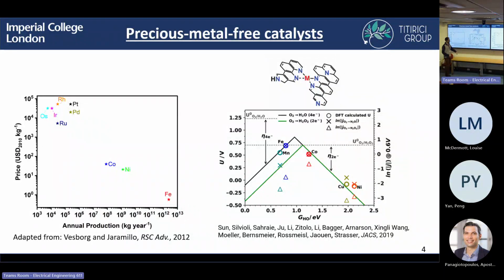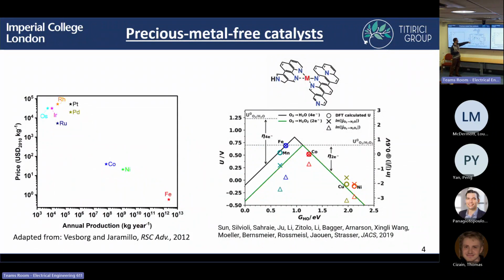And just to clarify for those of you who aren't electrocatalysis people, this is essentially a volcano curve where we see the binding energy to the oxygen reduction intermediate and how this scales with the binding energy. Ideally, we want to be as close to the top of the volcano as possible, because then we're limiting the loss of the reaction. And ideally, we want to operate at around 1.23 volts. That's the theoretical potential. But there's always some loss in the reaction due to scaling of intermediates binding. And so normally we're operating at, say, a loss of 0.4 volts.